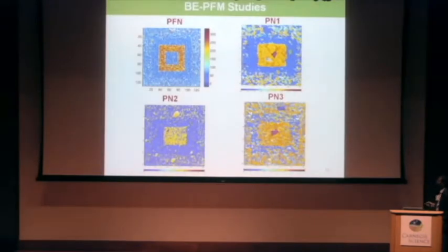In order to confirm the ferroelectric nature of all the thin films, we studied band excitation PFM measurements. Here we poled the sample with positive and negative 5 volts, and we can see the phase contrast in the positive and negative areas. From this we can tell that all the composite thin films exhibit ferroelectric character. But this behavior can also be seen in some non-ferroelectric materials due to electrostatic effects. So in order to rule out that this behavior is due to electrostatic effects, we carried out some other studies.